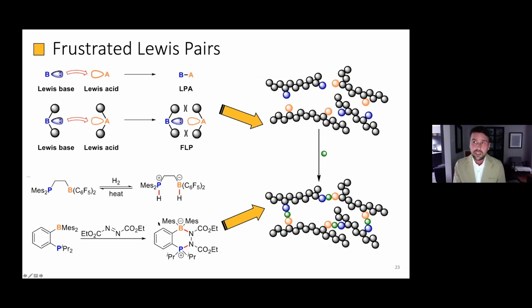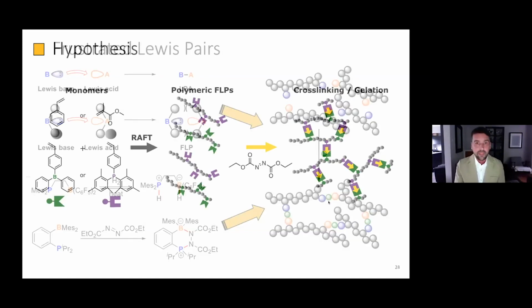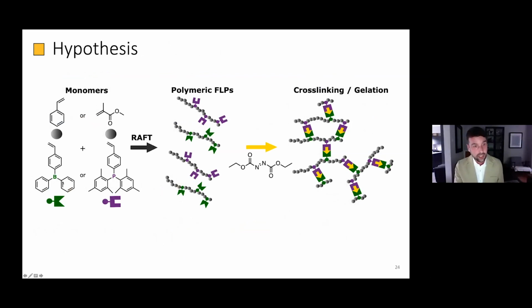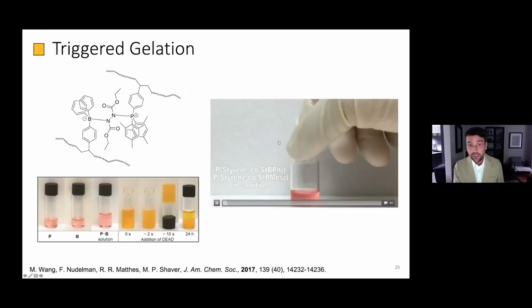And what we wanted to do was to say, well, what happens when we extend this to polymer chemistry? Can we prepare a Lewis acidic polymer and a Lewis basic polymer that would then not interact with each other in the solution state at all, or in fact at surfaces? And then when we put a small molecule in, we get some sort of a response. So the concept is we take a designer boron and a designer phosphorus-based polymer, do copolymerizations with styrene or methyl methacrylate, traditional radical polymerization, to make these polymeric frustrated Lewis pairs, and then induce cross-linking or gelation to be able to affect a chain. So hopefully this video is playing for you guys.